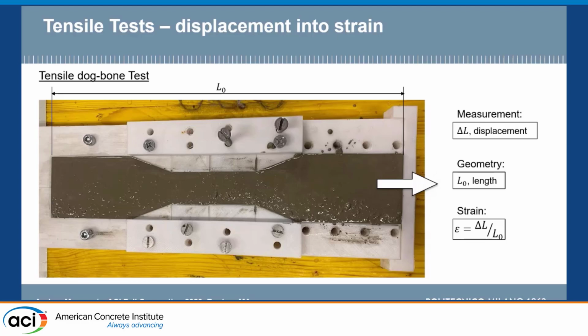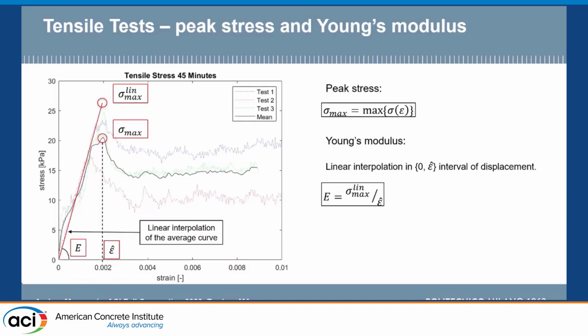Then for the tensile tests, we have processed the output of the test more. We have also computed the strain, so as to obtain a stress-strain curve. We obtained the strain simply by dividing the displacement measured during the test by the initial length of the sample. And this is what we got from the tensile tests. We were interested again in the peak stress. And then we have also tried to measure a parameter that belongs to the solid state, but we measured it also here in the plastic state: the Young modulus, by linear interpolation of the first branch of the curve until the peak stress.